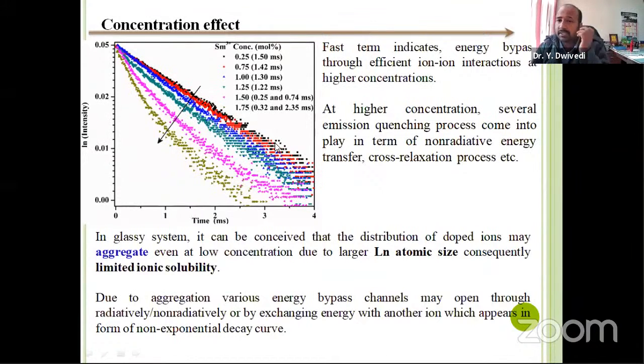This fast term appears, as I said before, because the lanthanide ion's ionic radius is a bit big. Its ionic solubility is limited, so it has a tendency to form clusters or aggregation. Due to that, it opens up pathways to relax the energy through the unexcited ions, meaning excited ions transfer energy to unexcited ions, moving to different transitions. That's why new terms are appearing.